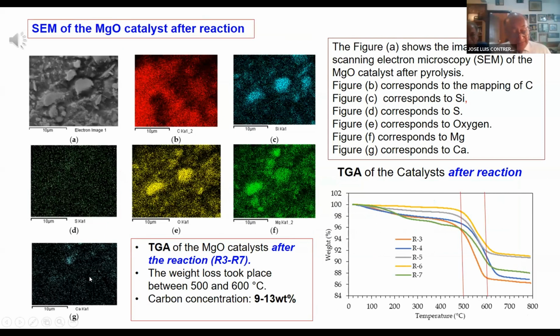The analysis of the carbon deposited in some catalysts was carried out by thermal gravimetric analysis, obtaining a carbon concentration of 9 to 13 weight%.